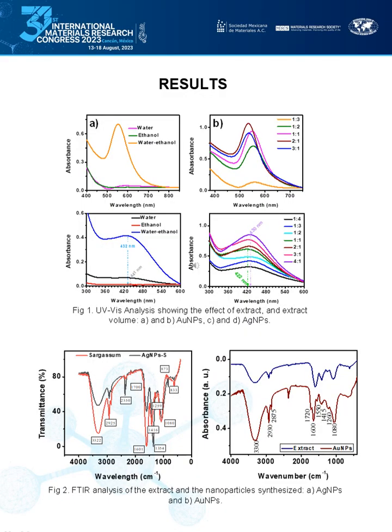As a result, the type of solvent used in the extract was first evaluated, that is, ethanol, water, and a 50% ethanol water mixture. As can be seen in the UV-vis figure, the water ethanol based extract showed the best results, since a more intense absorption band is observed, indicating the presence of higher concentration of nanoparticles. The result is observed for both silver and gold nanoparticles.